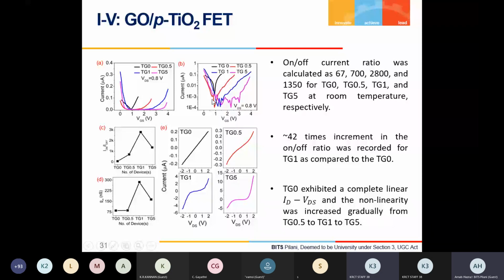Now, this type of device is a depletion mode device. Depletion is a normally on device. So when the gate to source voltage is 0, the device is on and shows some current. Then when the gate to source voltage reaches a particular value, the device is off and shows the minimum current. From this on and off current, the ratio is the on-off ratio. Here the on-off ratio measured for these four devices is 67 for pure graphene oxide, 700 for TG0.5, 2800 for TG1, and 1350 for TG5.